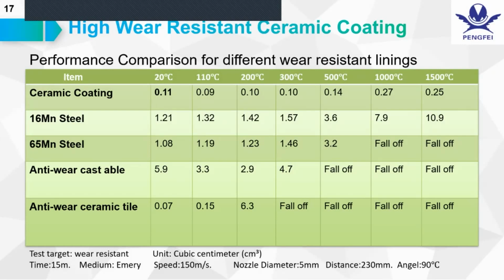This data is about several ways you may take during your maintenance, for example coating. As I explained, ceramic coating and different wear-resistant steels like manganese steel, and also castables. We may all have heard about castables and ceramic tile to protect the pipe. You can see how, as the temperature changes under the same working conditions, we test the results for the wear rate.